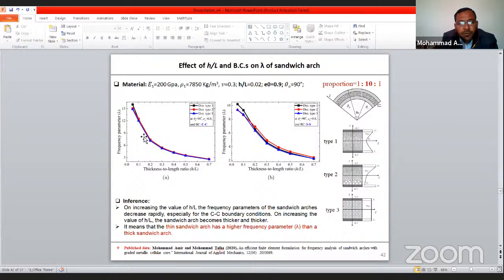By increasing the thickness to length ratio, it is changing from thick structure to the thin structure. Let's say by decreasing the thickness, by keeping length constant, its h by L ratio is decreasing. So in that case, the frequency parameter is getting higher and higher. So it can be concluded that the frequency parameter is higher for the thin structures, thin sandwich arch, than a thick structure.